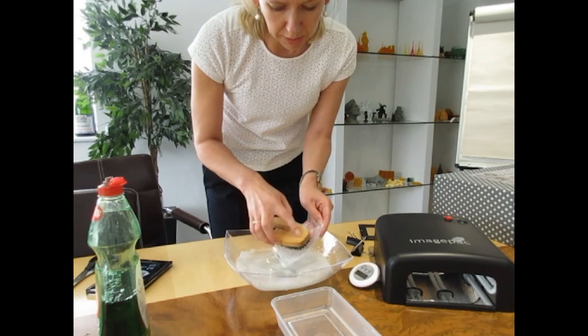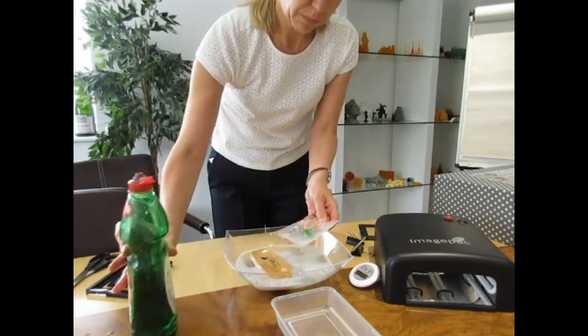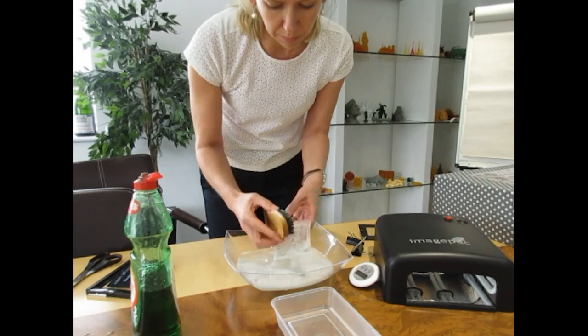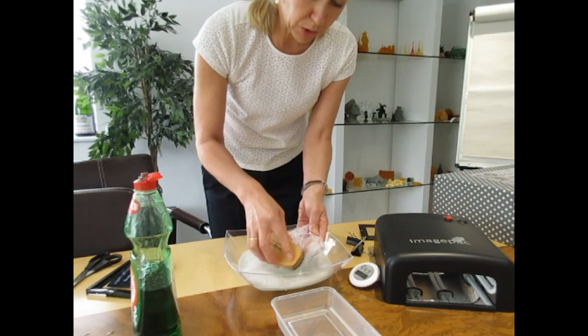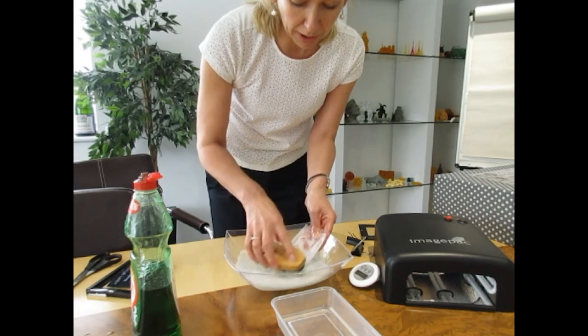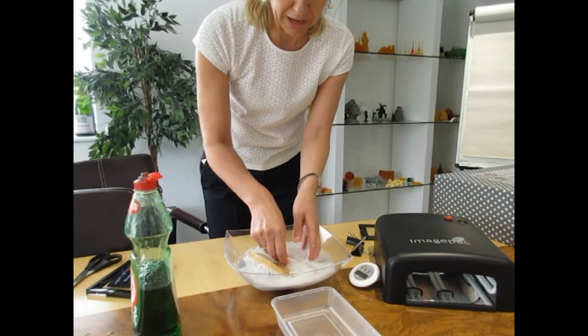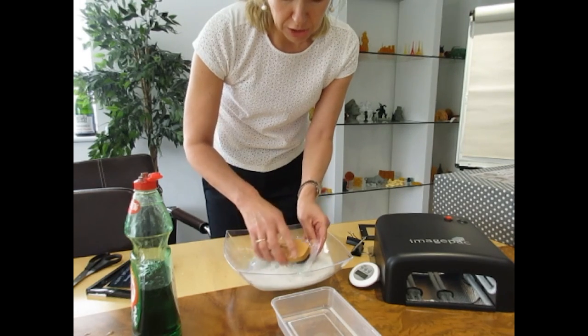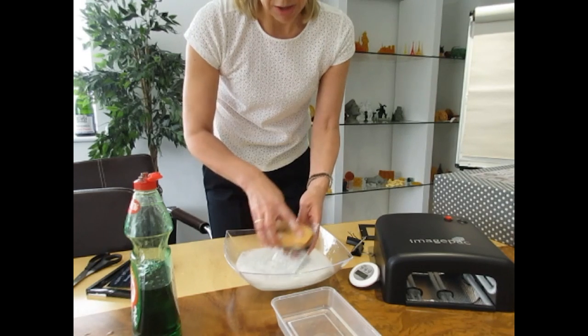With designs like this heart, you can be quite rough when washing, but if you've got fine text you'll need to be quite gentle. I did 15 seconds and two minutes for this exposure. The polymer is quite reactive, so you may need to adjust the times depending on your design. If you have designs with a lot of clear area, the light goes through faster so you may need to reduce your times. If you have very detailed text, you may need to increase them a little to hold the detail. These times are a kind of average to start with.